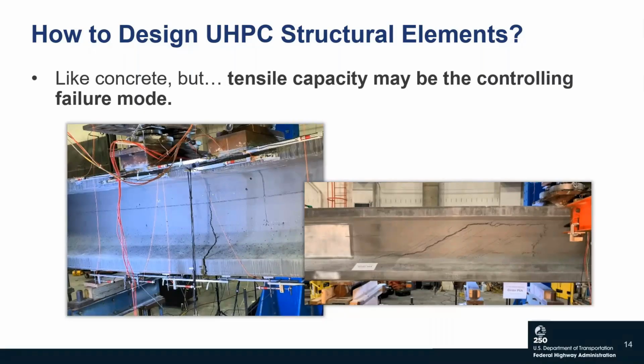That failure mode will be checked and designed for, and that is covered in the guide. The picture here on the screen shows a UHPC girder tested near Turner-Fairbank in flexure, and this one is in shear. As you can see, that is the crack that you'll see around the point of failure, which corresponds to the crack localization of the material, the point at which you start to lose that tensile bridging capacity.